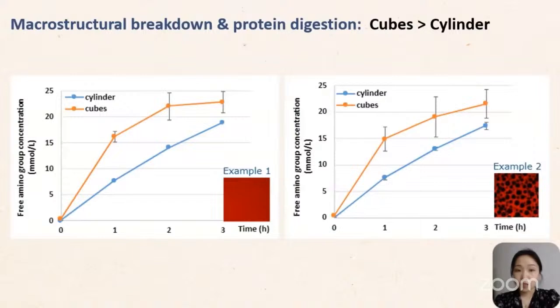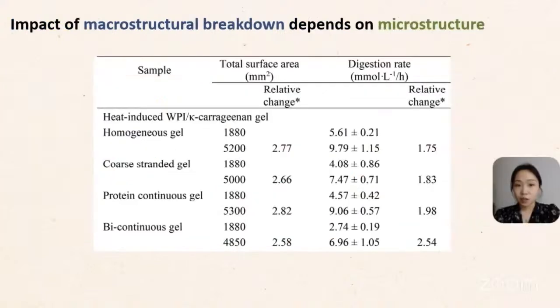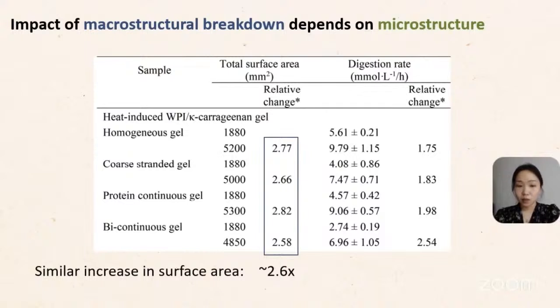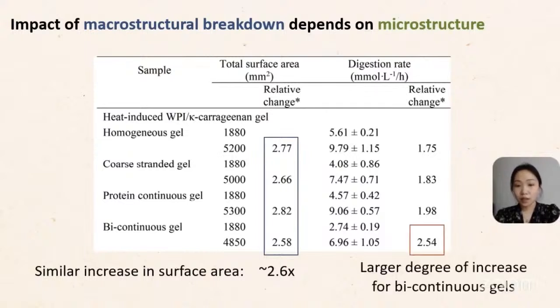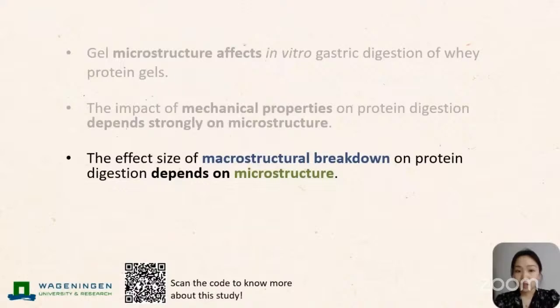As expected, for all the gels, the cubes were more digested than the cylinders due to their larger total surface area after macrostructural breakdown. But if you look closely at the results, you will find that for the gels with different macrostructure, even though they had a similar increase in surface area, the bicontinuous gels showed a larger degree of increase in digestion rate compared to the other three gels.